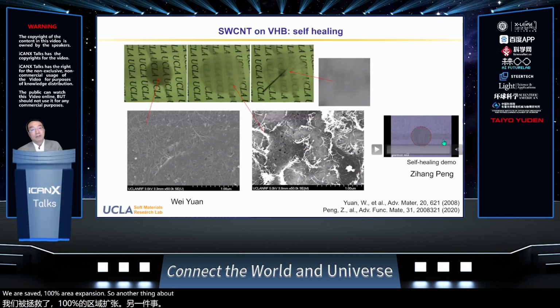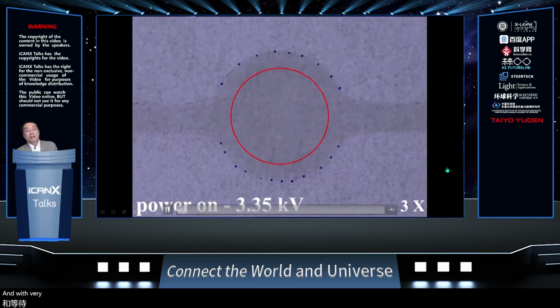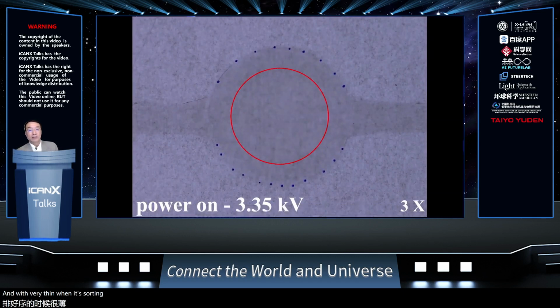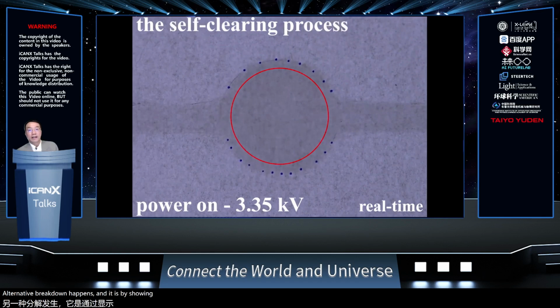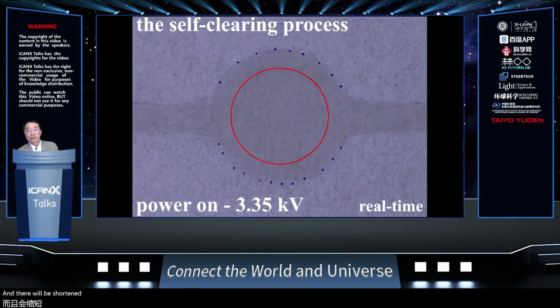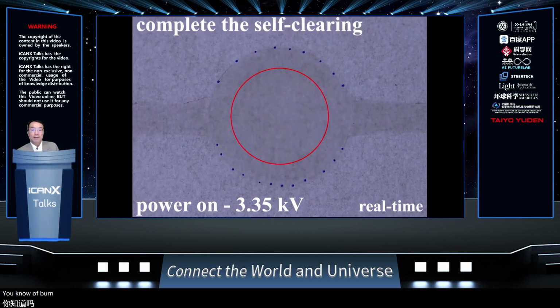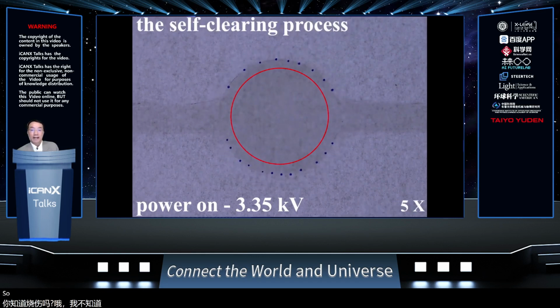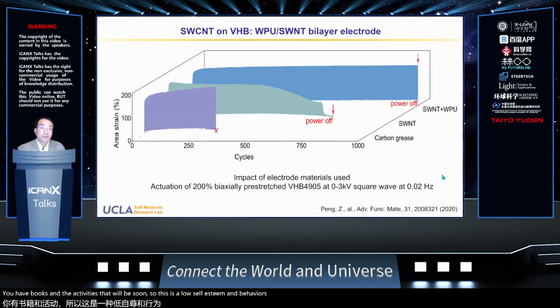Another thing about the carbon nanotube here is that at 100 kilo ohm per square sheet resistance, this coating is extremely thin. When it's very thin and a dielectric breakdown happens, like the one shown here, applying the voltage again will cause shorting. That shorting causes local heating and will burn off the carbon nanotube around the short. After that, the short is healed, and the actuation can resume. So this kind of self-healing behavior is useful if you care about the operational stability or lifetime of the